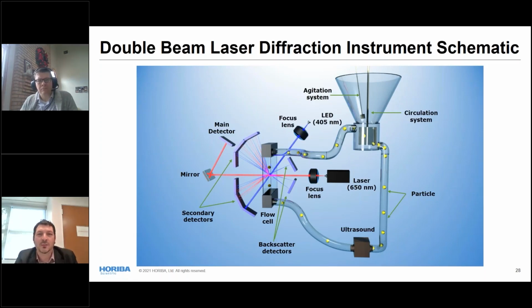In the case of our analyzer, we measure all the particles with all the light sources at the same time, so you have a compilation of results from all. There's no specific limit threshold of particle size; it's more of a range. The red laser intensity decreases, it scatters, and then the blue starts to increase. As you can see in this plot, the backscatter detectors mainly scatter the blue light. We don't have red laser scattering in the backscattering detectors. The reason, in physics, is that as you decrease the particle size, you increase the angle of scattering. So small particles mainly scatter the blue light and only at high angles. We don't have any red laser scattering at high angles.